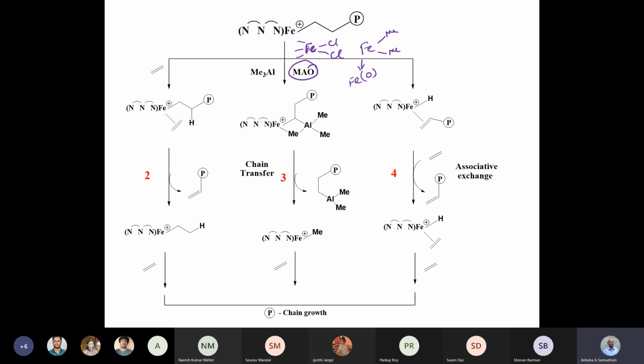I can also have a situation where I do hydrogen abstraction and generate FeH as an intermediate species, which can initiate the polymerization process, or FeMe as an intermediate which can initiate the polymerization process. Once it is initiated, the alkyl chain can be generated from ethylene, and then the growth of the polymer chain can proceed, resulting in the formation of very large polymers. Termination happens with beta hydride elimination, and that is what is indicated here.